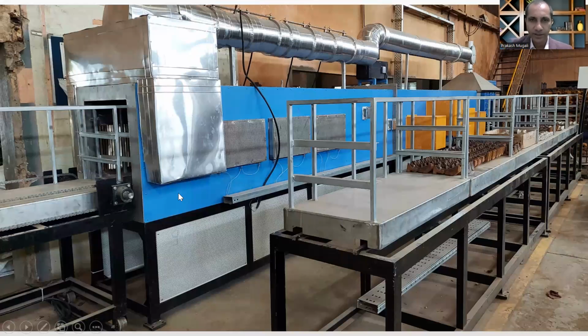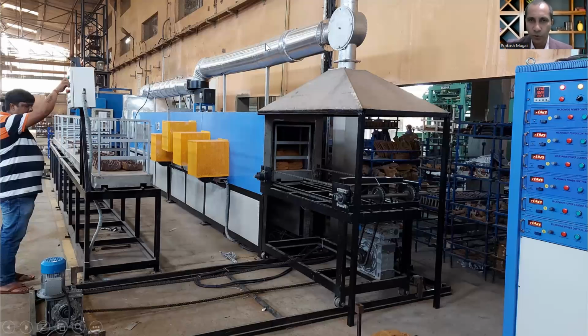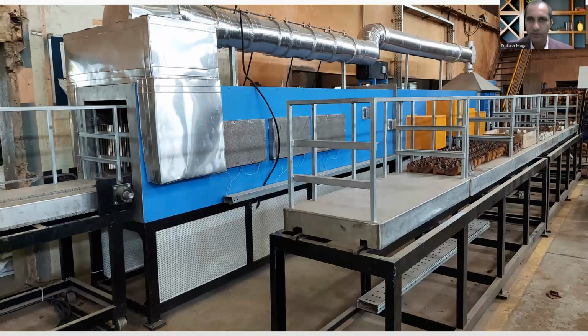So this is the other end of the oven, where the trolleys are coming out. This also has a heated air circulation. If you can see the hood, from there is a ducting that carries the heated air. Microwaves are heating these cores from the left side and the right side, and the moisture is taken out, and the heated air entering carries the moisture out of the dryer, and then it is connected to an exhaust here. The proportion of exhaust to recirculation of the air can be adjusted with the adjustable baffle plate here, so that you can control the fresh air entry into the system or the air changes of the dryer.